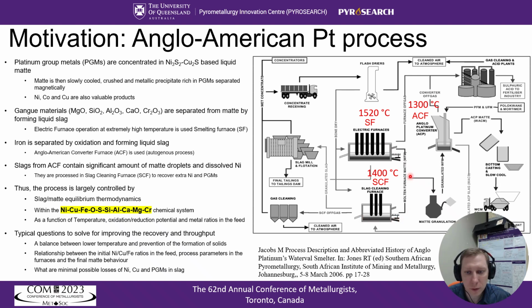Slag cleaning furnace produces additional amounts of matte, which can contain PGMs, and it is returned either to smelting furnace or to the converting furnace. Thus, in spite of different temperatures and oxidizing-reducing conditions, the process is largely controlled by slag-matte equilibrium thermodynamics within the nickel, copper, iron, oxygen, sulfur, silicon, aluminum, calcium, magnesium, chromium chemical system.